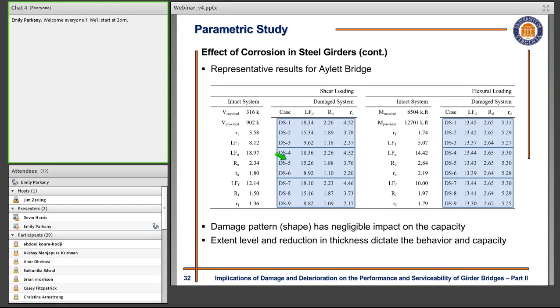The second 3 cases refer to the case where we have a triangular shape for the damage, and the last 3 cases are trapezoidal cases. As you can see, for each of these categories, as we go from case 1 to 3, case 5 to 6, and 7 to 9, we have more reduction in the capacity of the system as we increase the intensity of the damage. But if you compare these boxes together, you can see that the shape of the damage does not have major impact on the values that we have.